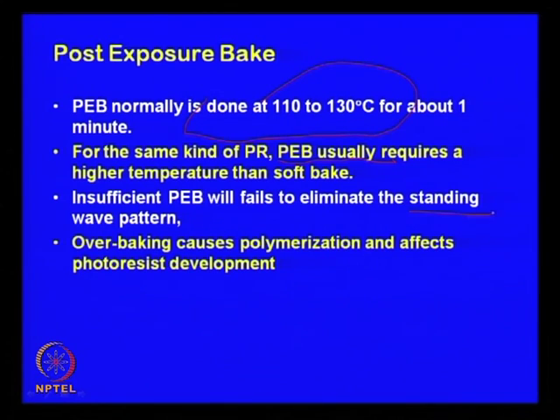This I will just tell you what it means. Insufficient post exposure bake fails to eliminate the standing wave pattern. Overbaking causes polymerization and affects the photoresist development. So, overbaking at this stage leads to polymerization of the areas which were supposed to be dissolved away during the development stage.